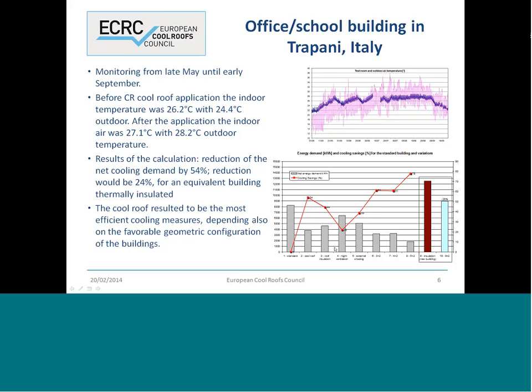We also tested different strategies like roof insulation, night ventilation, and external shading, and the cool roof was the most performing. Of course, lower values can be reached by combining different technologies. 24% cooling energy savings were calculated for the same building if thermally insulated. This case study gave excellent results, also because of the building geometry, which was very favorable to the high surface of the roof with respect to the volume to be heated.